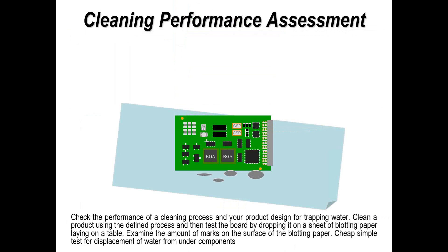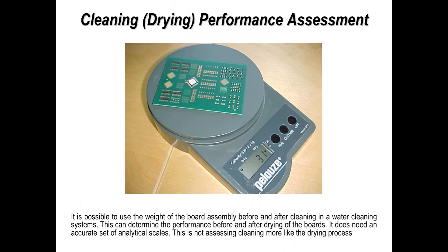The boards used were probably scrap — it's quite a severe test — but it worked surprisingly well. You can actually see the difference in drying cycle temperature and force being applied. It's crude and simple, but if you're not worried about the boards, it works. That's a way of assessing any moisture still left underneath components. You can also do weight gain and weight loss, though you need a very sophisticated set of balances. You'd weigh the boards before and after the cleaning process, or look at them before and just after the drying process.